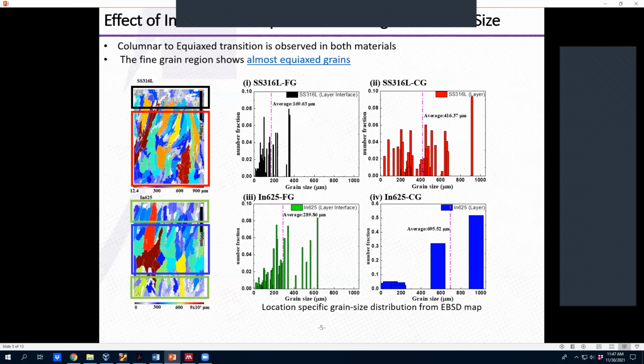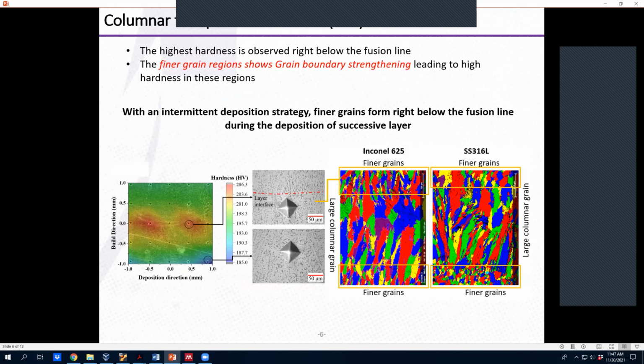We see that the fine grain region for both materials shows almost equiaxed morphology, and the grain size varies between the columnar grain region and the fine grain region. So the first question is where these fine grains are forming, and then how they are forming in the WAM process with the intermittent deposition strategy. To figure out the location of the fine grains, we took hardness plots at different locations across the layer interface, and we found that the region right below a layer interface shows the highest hardness. From the grain size maps, we also know where the fine grain regions are. So we relate the high hardness region with the fine grain regions, and from the hardness map, we conclude that the fine grains are forming right below a layer interface.